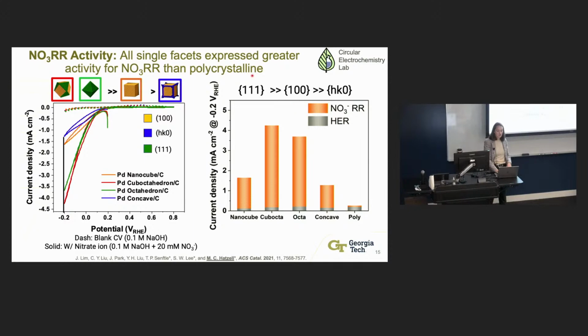And the interesting thing that arose here is that this 111 facet really seemed to have a preference for nitrate reduction. Just a reminder, palladium is the metal that doesn't bind nitrate. And so we actually think palladium is not so great with nitrate reduction. And so what we're really trying to do is amplify that. And so what it's saying is that, yes, palladium is not great for nitrate reduction, but if you do want to design your catalyst so that it has some activity, you'll want to look for designing the catalyst with the 111 facet.